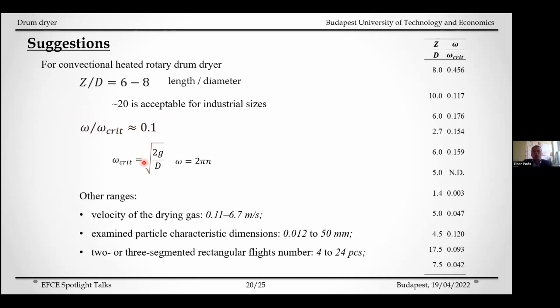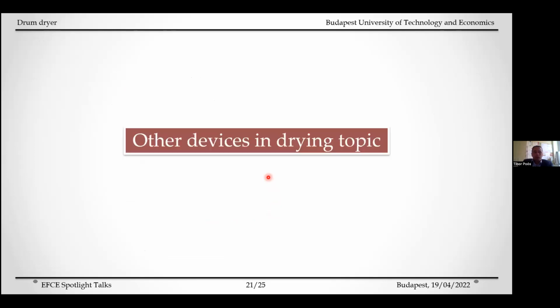The velocity of the drying gas is mainly determined by the particles density, size, and drag coefficient. So depending on the material, the value of the velocity varied in a wide range between 0.1 to 6-7 meters per second. And in the last slides, I would like to show you some devices in the drying topic which can be found in our laboratory.